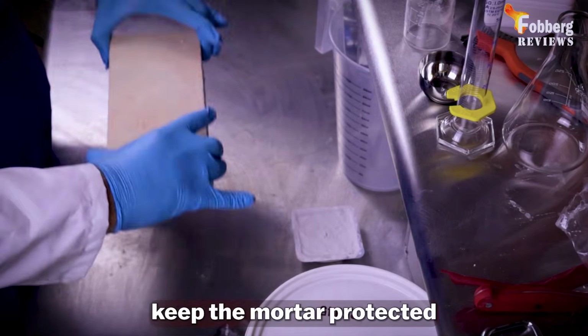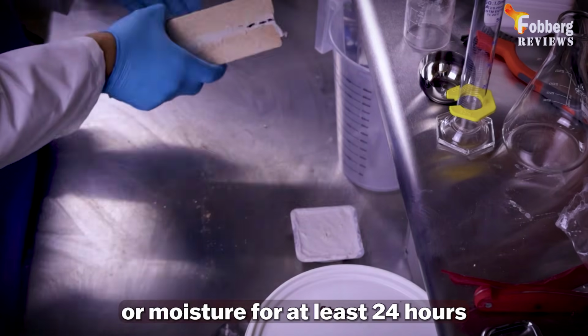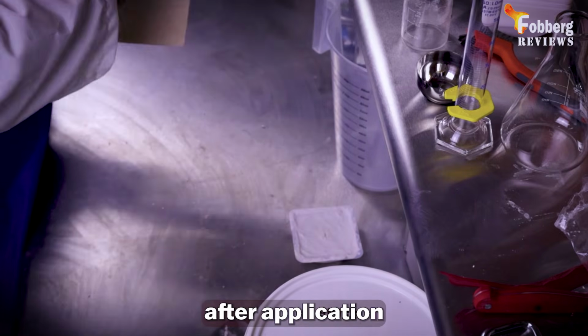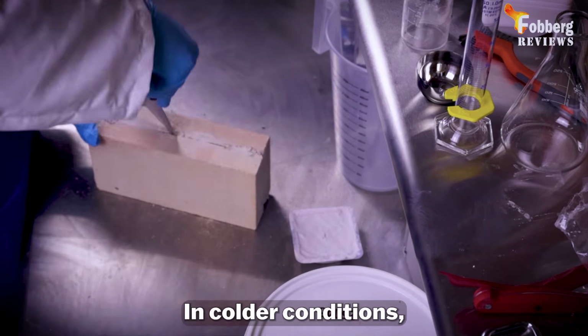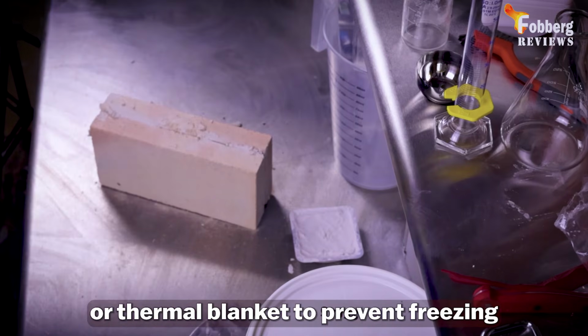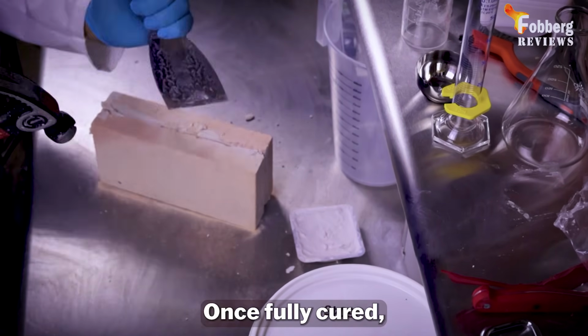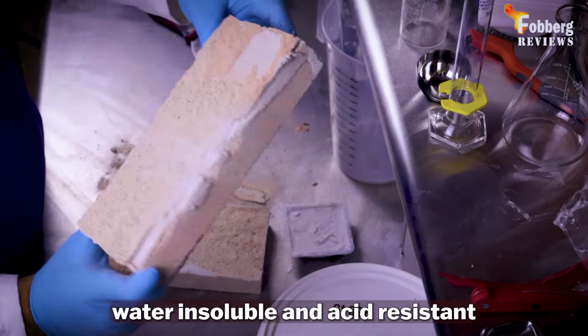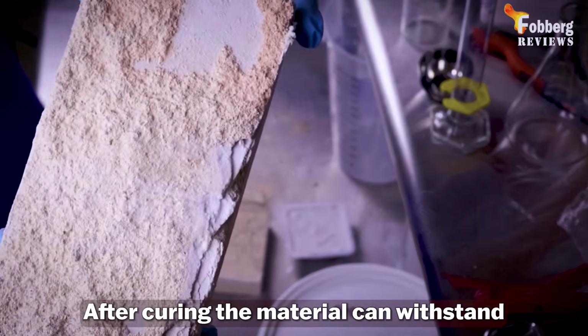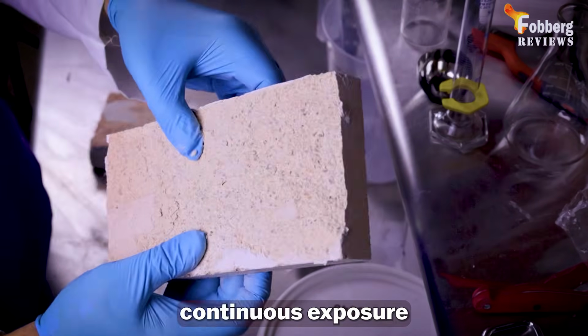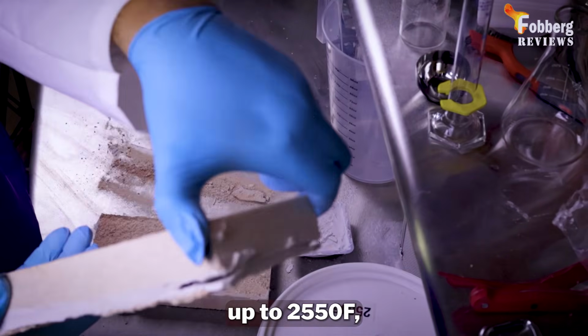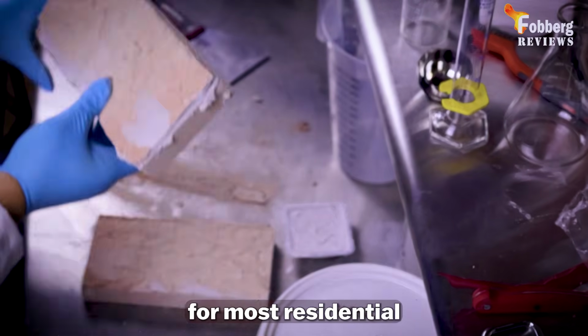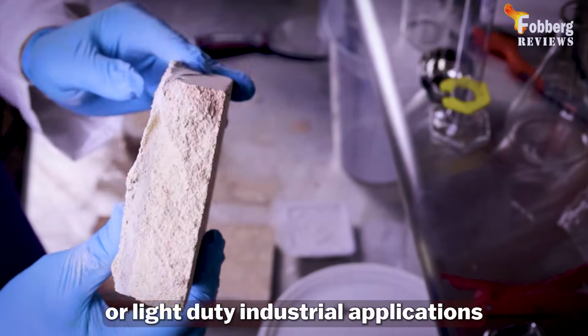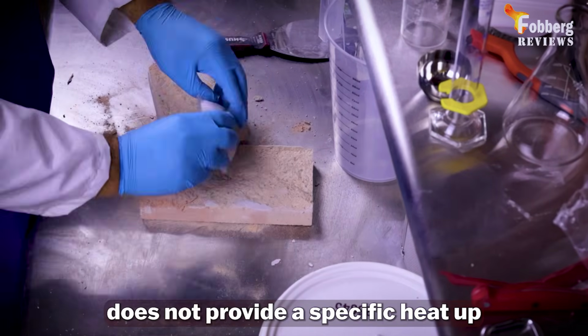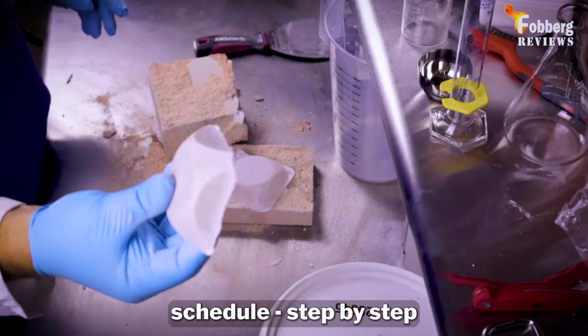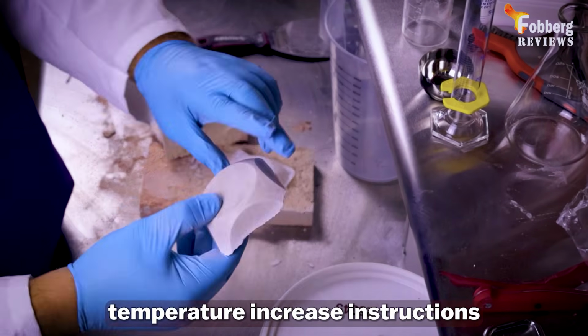Curing requirements: keep the mortar protected from rain or moisture for at least 24 hours after application. In colder conditions, use plastic sheeting or a thermal blanket to prevent freezing. Once fully cured, the mortar becomes water insoluble and acid resistant. After curing, the material can withstand continuous exposure up to 2550 Fahrenheit, which is more than sufficient for most residential or light-duty industrial applications. However, the manufacturer does not provide a specific heat-up schedule, step-by-step temperature increase instructions.